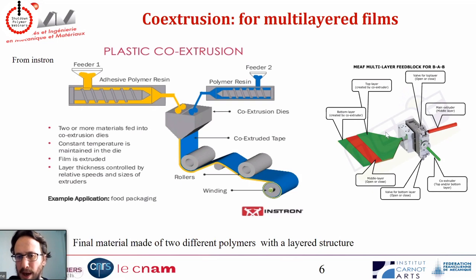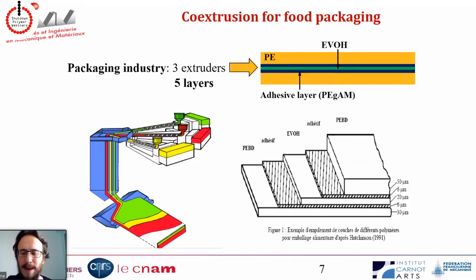Depending on the shape of the die, you can have 2 layers, one on top of the other, or 3 layers, one polymer in between 2 layers of the other one. So that just depends on how you structure your feed block and your die. This strategy of co-extrusion is really well known and has been used in the packaging industry for decades. And actually what you do in the packaging industry is you use one flexible polymer, so usually polyethylene, and one glassy polymer that is a really good gas barrier, which is usually EVOH. So the idea is that the polyethylene is really cheap, really easy to process, and really flexible, so to wrap your food so it cannot be wasted, it's good.